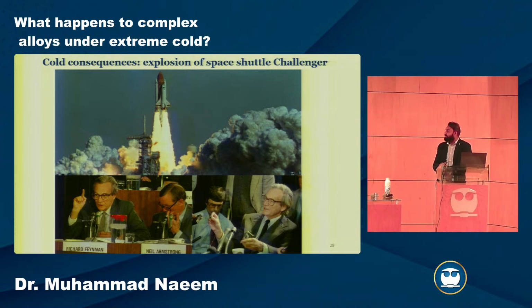He was also part of that commission, and they were investigating, and Feynman was a genius. They had these O-rings to seal the different components. He took a part of that O-ring, and you can see in his hand he's holding this C-clamp. He put that material in iced water, at 0 degrees centigrade, and then took it out. First he showed that before putting it in water, it was flexible. Then he put it in iced water, took it out and put it in the C-clamp again, and now it was not flexible.